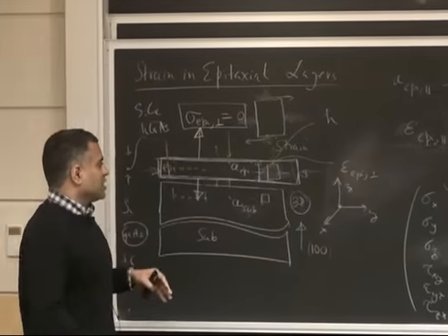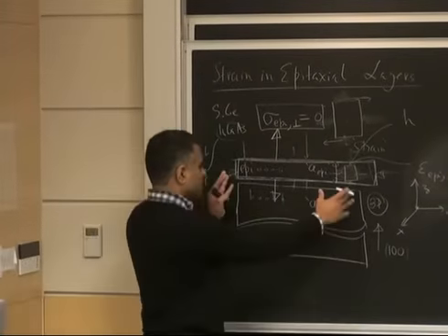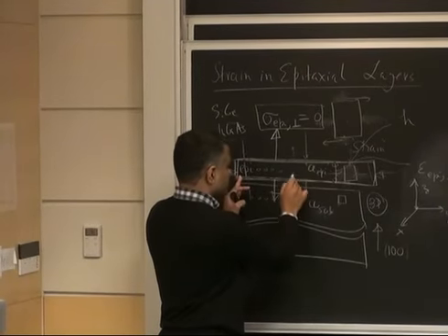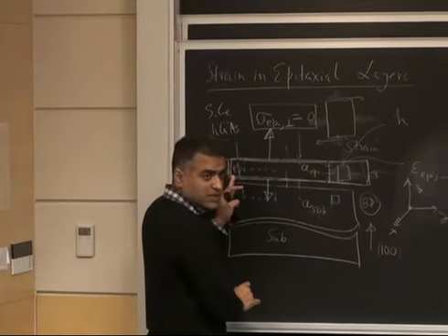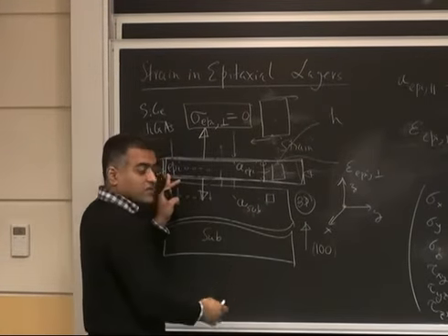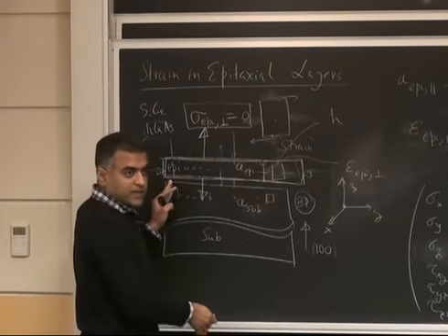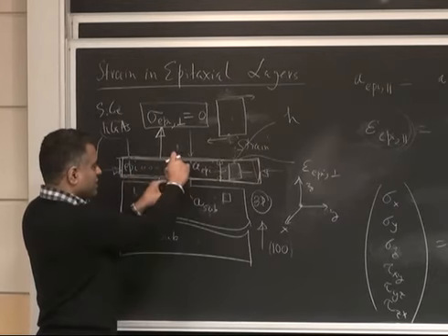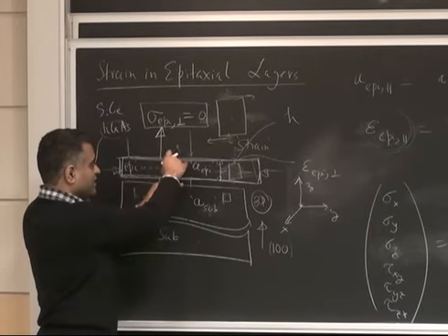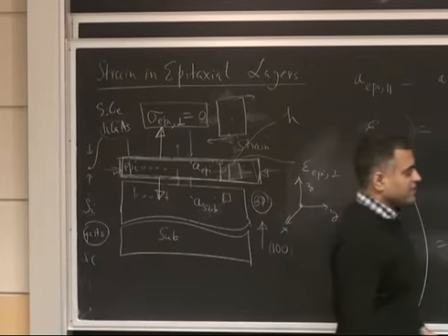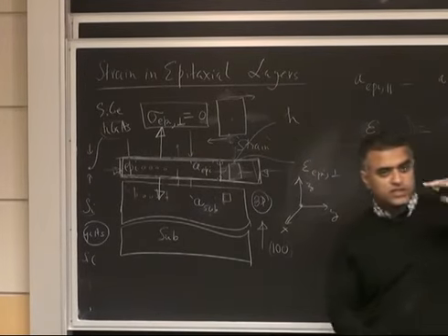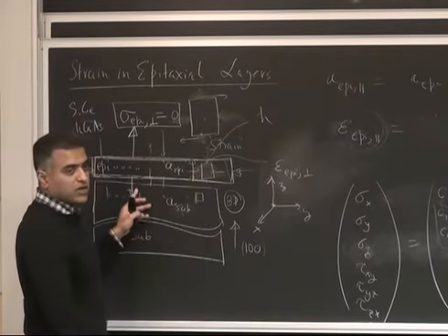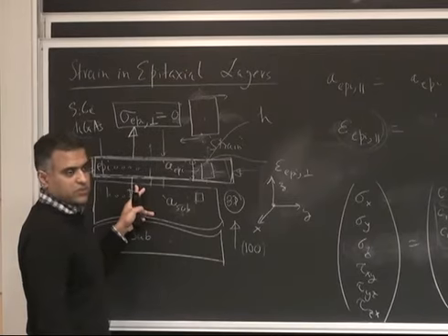And then we'll see that there will be another possibility that instead of straining completely, it can actually form these defects or dislocations where there will be broken bonds here. And we'll ask the question, what is the energy cost of forming those defects? And then as you keep growing this thicker, the energy cost of remaining coherent, which will be this half kx squared term, will grow linearly with the thickness, but the energy cost of forming defects will grow only logarithmically, very slowly, almost remain constant if you might.